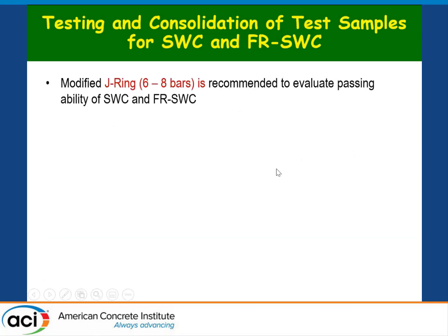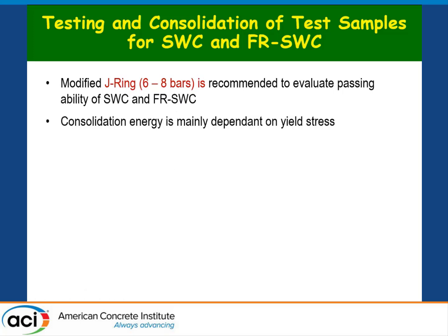So in conclusion, really the takeaway from this presentation is that we can use a modified J-Ring, whether it's 6 bars or 8 bars, to evaluate the passing ability of super workable concrete or fiber reinforced super workable concrete. In terms of super workable concrete, we recommend using 8 bars. In terms of the FR super workable concrete, depending on the length of the fibers, you need to have 6 or 8 bars. We try to keep 2.5 lengths of the fiber as spacing.